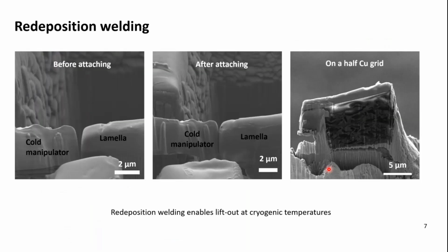The most difficult part in cryo-TEM sample preparation is, of course, cryogenic lift-out, because you cannot use selected area deposition like you do at room temperature to weld your sample to the micromanipulator. However, there are several ways to make the approach possible. One way is redeposition welding. In this process, you can mill the region near where you make contact between the cold manipulator and your lamella, and redeposited particles will be splashed into the gap, and your sample can be welded within 30 seconds. And this way, you can extract your samples, and you can place your sample onto a half grid in the same manner, and you can thin down until you have electron transmission.